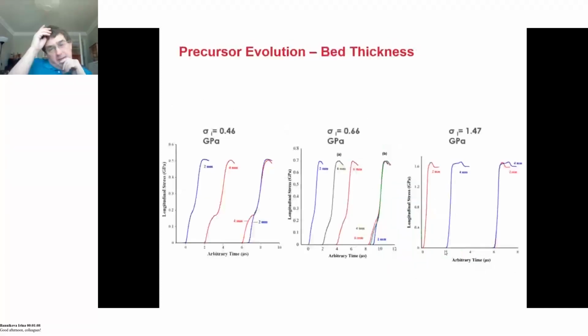Now, as you change the bed thickness, you can find how the compaction wave, this initial precursor wave, sorry, goes ahead of the material, and you can find its velocity. So here we have, at this particular stress, a couple of stress pulses for different thicknesses of bed, and this is compared. Again, different stress, different bed thicknesses, again showing them compared, and then at a different stress, again, very little change above 1.5 gigapascals. So this compaction behavior is in the region of 0 to 1.5 GPa.